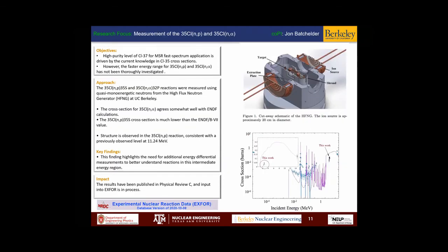And finally, simulations without data sometimes are not that useful. So we have also spent a little bit of time in year one of the project looking at chlorine-35 cross sections. The importance of this is that it relates to the level of purity required in chlorine-37 for fast spectrum MSR applications. Our experiments have shown that the (n,alpha) cross section agrees well with what is published in the literature. However, the (n,p) reaction is much lower than what is available in the evaluated nuclear data files. Therefore, this could be an area to investigate further. Our experimental results are currently being processed in the X4 database and should be available in the ENDF library soon.